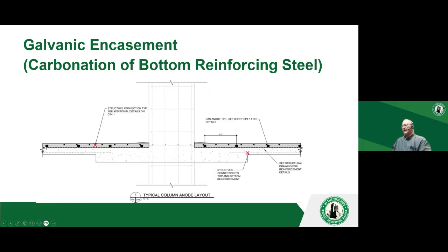Basically what happened here, we have a parking garage that's underground, and you had a lot of carbonation on the bottom steel, chloride contamination on the top. They were going to mill the entire top. They shore this, they mill it, remove all the top steel. There's a lot of corrosion damage, potholes and stuff on the top right now. There's still some chloride contamination, but at the bottom, it was carbonated right up to the bottom of the reinforcement.